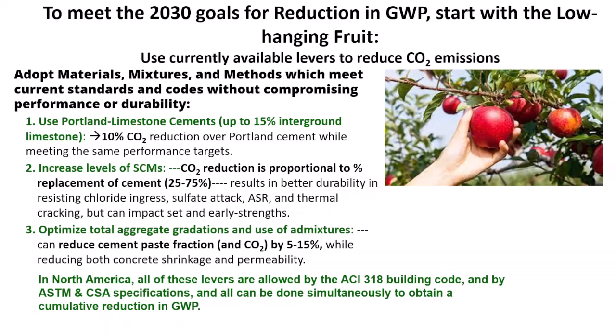And in Europe and a lot of Asia, in the newer plants, they're using up to 6 different aggregate sizes and combining them to get optimized gradation, which can reduce the paste content, which will not only make more sustainable concrete, you get better quality concrete, because permeability of concrete is related to the paste fraction. The more paste you have, the higher the permeability for a given mix. And you're going to have more shrinkage and volume change because that's related to the paste fraction. So it's a low-hanging fruit that could save another 15% of the CO2 just by changing the cheapest thing in your mix, often the aggregates. But it requires more bins at the ready-mix plants, and it requires a little more optimization work.